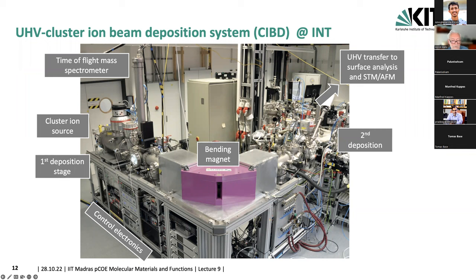So here the clusters are formed and they exit through a small hole, and a large fraction of them are charged. So we can manipulate them. The first manipulation we can do is with a time of flight mass spectrometer, so once we have the source running, we can determine the size distribution, and then we can change it by modifying the synthesis or processing parameters. And then we have a first deposition stage where we work with the clusters in their initial size distribution, and we can change the impact energy of the clusters on a substrate. And this I will show you in a little moment for a cluster-assembled metallic glass.